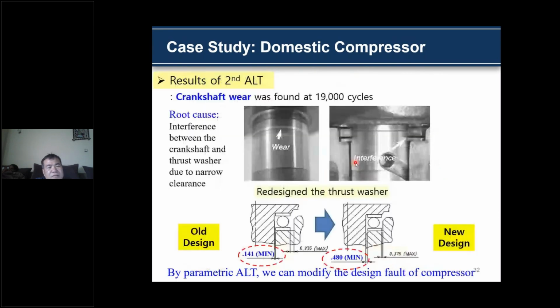This is another result, of the second parameter ALT. Crankshaft wear was found at 19,000 cycles. It came from the interference between the crankshaft and the thrust washer due to narrow clearance. This is the old design, and this is the new design. As an action plan, we increased the clearance from 0.1 to 0.5. By parameter ALT, we can modify the design of the compressor.